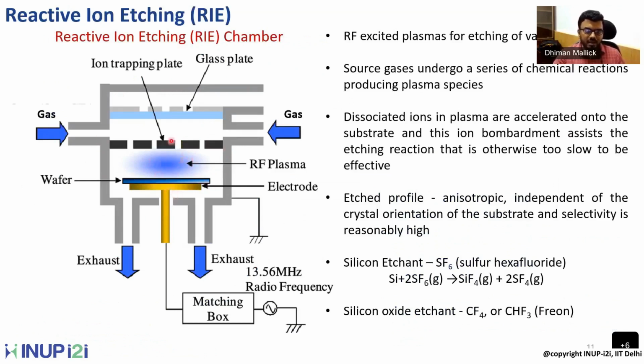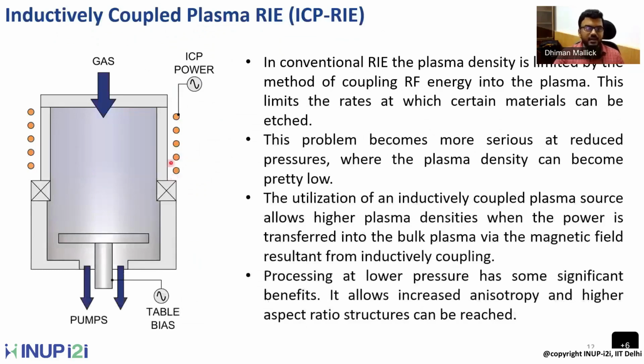Now the only thing with this reactive ion etching is that here you are creating the plasma based on a capacitive mechanism, right? You have two electrodes creating this plasma, and the potential or electric field created between these two electrodes also forces the ions to bombard onto the substrate. So these two mechanisms are directly related to the capacitive mechanism between the two electrodes. Now, if we can decouple these two mechanisms, we can increase the etching rate as well as the anisotropy.